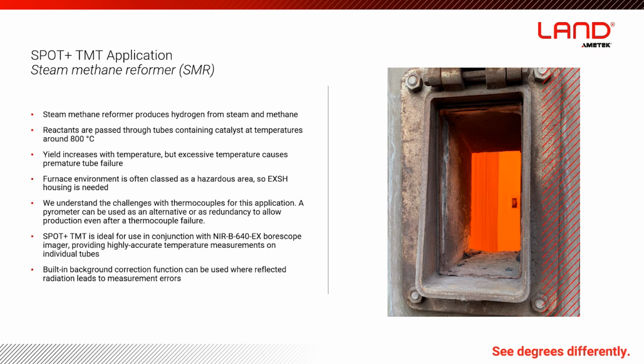We've got probably 40 years of experience supplying Cyclops pyrometers for this application. And you should probably think initially of the SPOT TMT as a fixed Cyclops, but with a load of additional capability and actually with an improved field of view. So versus a Cyclops, you can see a narrower tube from further away. And that's really key in these applications because you want to really recreate what a fixed thermocouple might be doing on the furnace. And we can do that from outside the furnace, which should be far more reliable than a skin thermocouple, should be just as accurate, if not more accurate. And in terms of maintenance and accessibility, constructability, reliability, it's hugely advantageous because of the remote nature of the measurement.